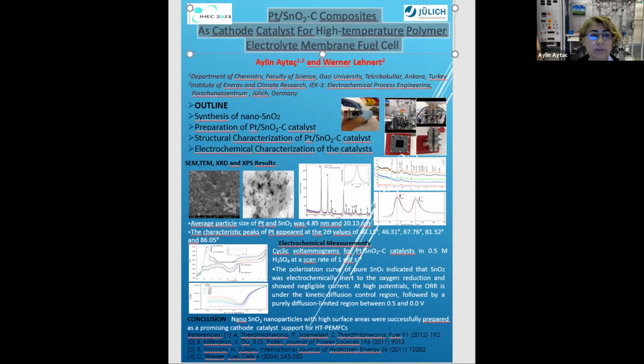voltammetry coupled with a rotating disk electrode showed improvement with the tin oxide addition. The synthesized catalyst performance was as good as the performance of the control commercial catalyst. High temperature polymer electrolyte fuel cell measurements performed at 160 degrees centigrade under dry gases, hydrogen and oxygen, showed 0.88 volt at the current density of 150 milliampere per centimeter square.